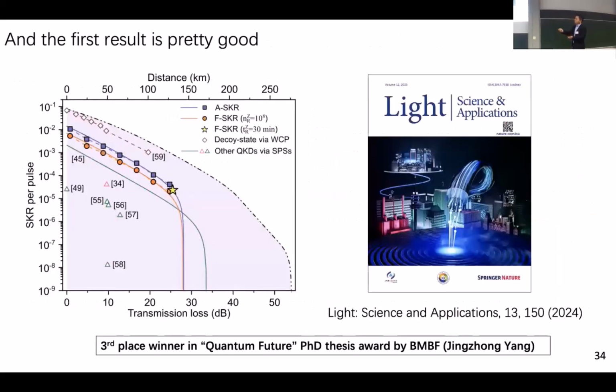So this is the results from our paper. This is a secret key rate as a function of the transmission loss, or you can understand as a distance here. So these are the result from our fiber spool in the lab, because here you can change the length of the fiber. This star here is our actual measurement over the 79 kilometer fiber, let's say the dark fiber, the field test. Okay.